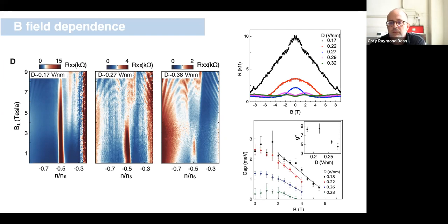There seems to be a curious regime of B field over which the gap initially begins as insensitive to magnetic field. This is field out of plane, I think, in this case. Or for some displacement field values, actually, it's even non-monotonic. So we see that for some range of displacement field, you can see that well on this plot, first the gap increases and then it decreases again. It's reflected roughly here. Okay, so again, exactly what this is telling us, we don't exactly know. And we're trying to study this further, to get a handle on whether there is a variation in the magnetic order of the ground state that depends on the displacement field value or the twist angle, etc.